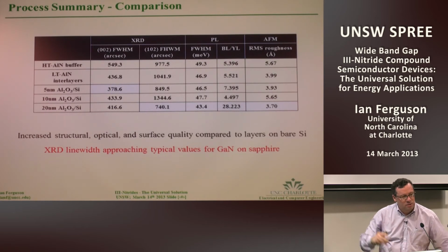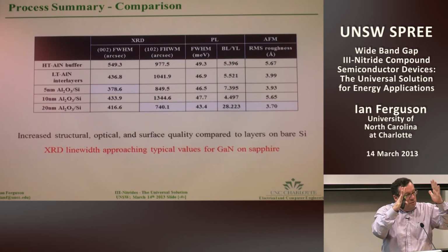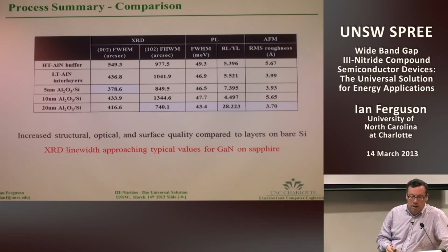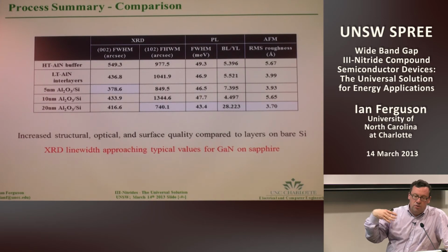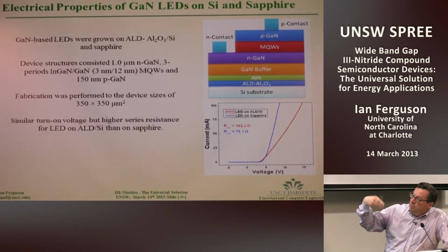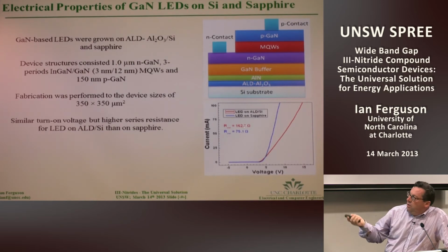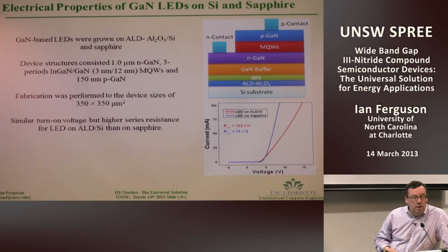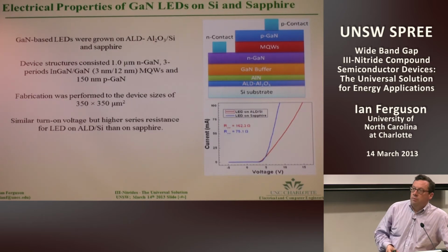Typically, the off-axis reflection gives you a sense of what these edge-type dislocations are within the material. So we were actually starting to get closer to what it was for growth on sapphire, and it was removing some of the thermal mismatch issues as well. So we started growing some type of LEDs on these structures. Typically, what you find for the LEDs on the silicon is that they tended to have a slightly higher series resistance. And that's really for two reasons. We were making vertical devices, so these thin layers, we weren't necessarily doping at this time, but also it was more difficult to p-dope the material, so that tended to increase your series resistance.